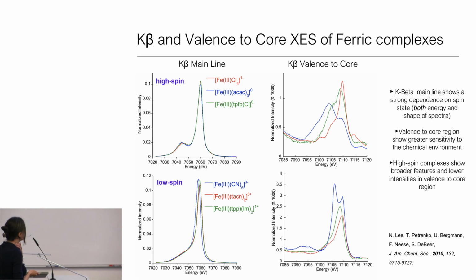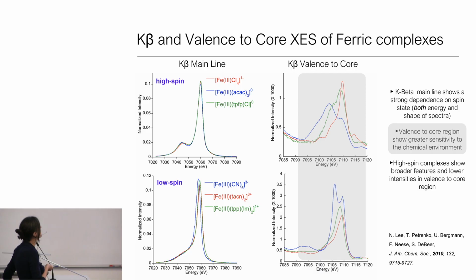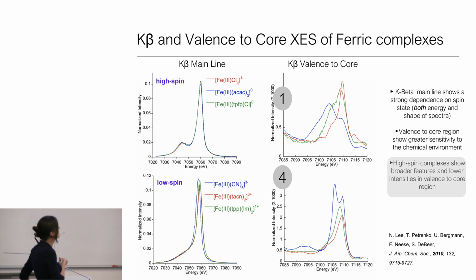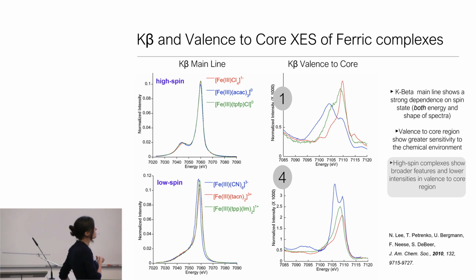Okay. What I want to move to now is, I've shown you there are clear fingerprints for low spin versus high spin. But one interesting thing to notice is that for different high spin or even different low spin complexes, the main lines aren't changing that much. But if we look at the weak valence to core, these are changing a lot. They look very different for different complexes. They also have very different intensities for high spin versus low spin complexes, where this axis is a factor of 4 different for the low spin versus the high spin. So there's a lot of information contained in these weak valence to core features.